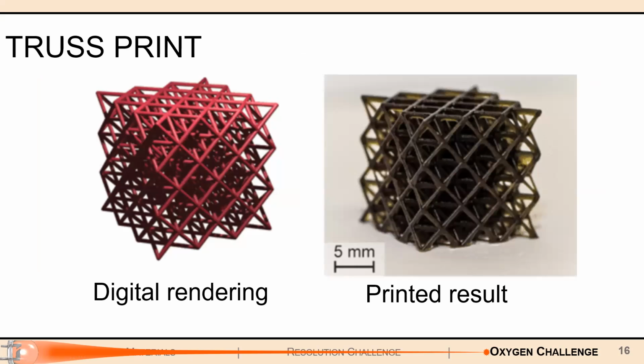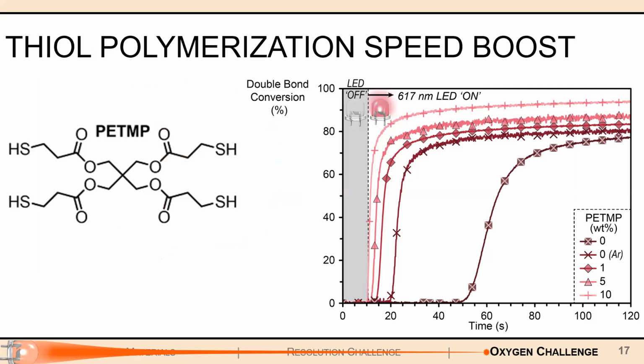So to make this more accessible to the average consumer, we dope our resins with a type of compound known as a thiol. This thiol, as you can see to the left right here, this PETMP, scavenges oxygen from the atmosphere and inside the resin. And by doing so, that'll prevent it from interfering with the catalytic cycle and allow your photopolymerizations to go to completion and a lot faster.